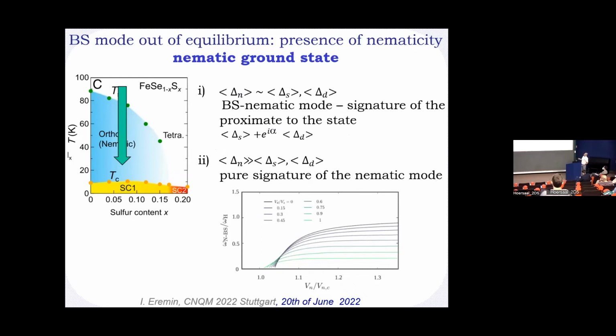But in this situation, you expect that the nematic transition is much higher than the superconducting transition. Now, once you are in the mean field nematic order, there are two differences. The first difference that we find is that once the nematic order is of the order of the superconducting d-wave order parameter, let me remind you that because you break the diagonal symmetry, you have an s- and d-wave order parameter which coexist. You still generate, in this case, a Bardasis-Schrieffer nematic mode by virtue of the same hybrid dynamic coupling.